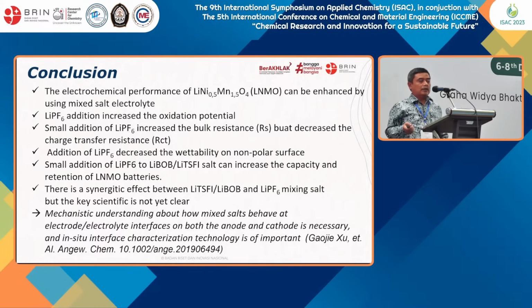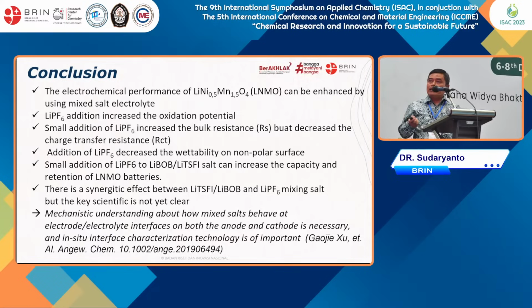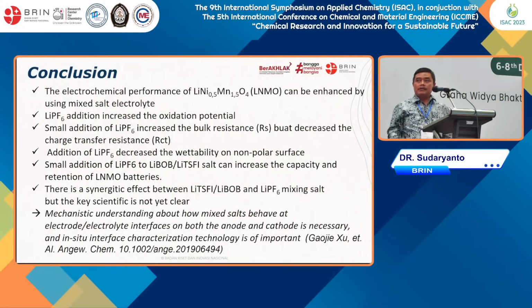I think time is limited, so let's go to the conclusion. As I showed, the battery performance of the high voltage LNMO battery can mostly be enhanced using the mixed salt as the base electrolyte. We can also see that with small additions there are some phenomena, but we can conclude that there is some synergic effect between the different electrolytes, especially LiTFSI, LiBOB, and LiPF6 mixing.